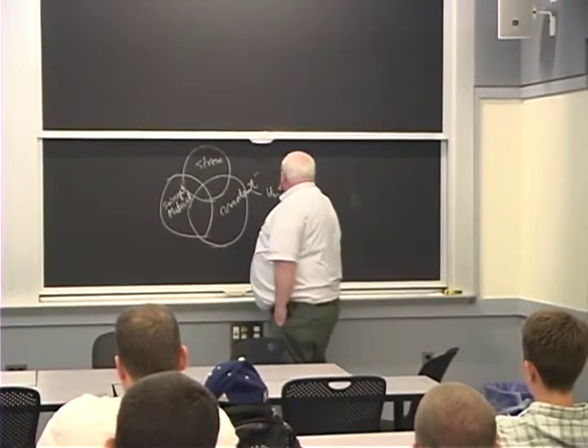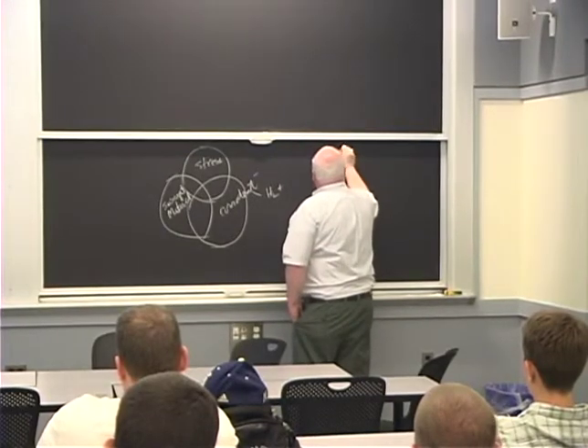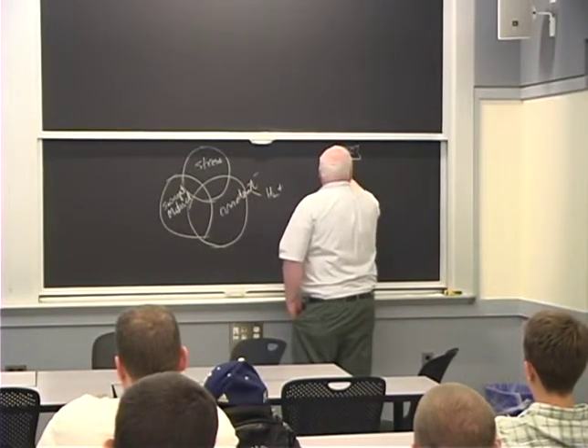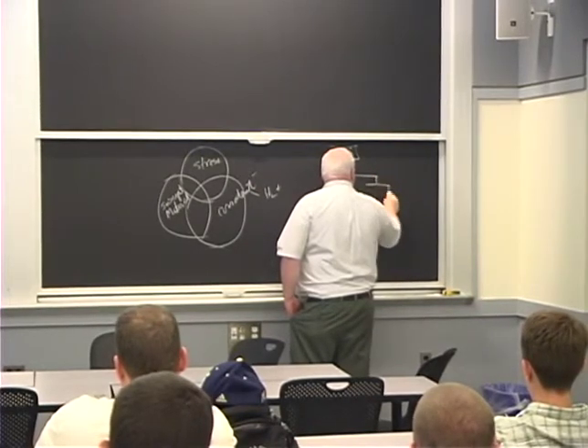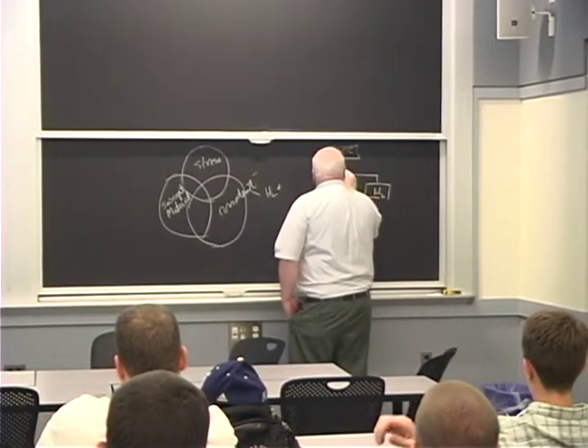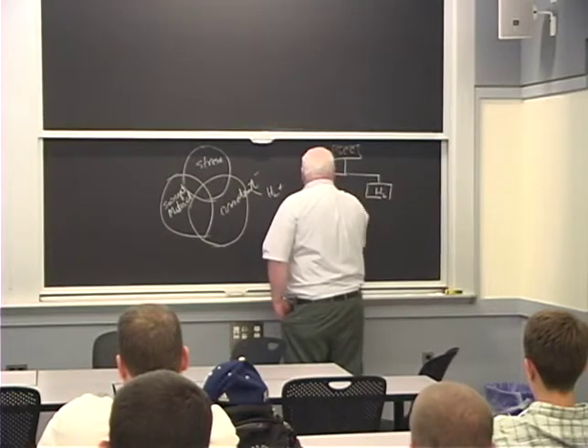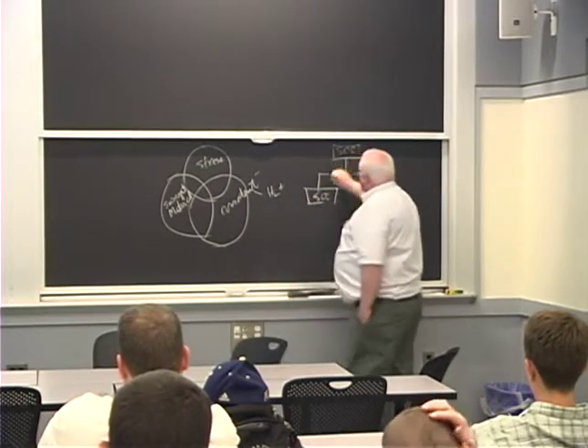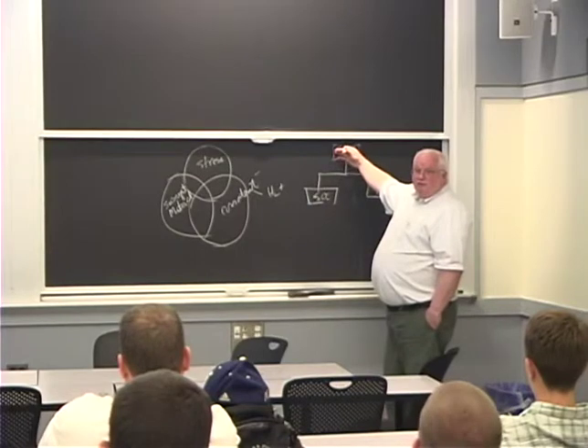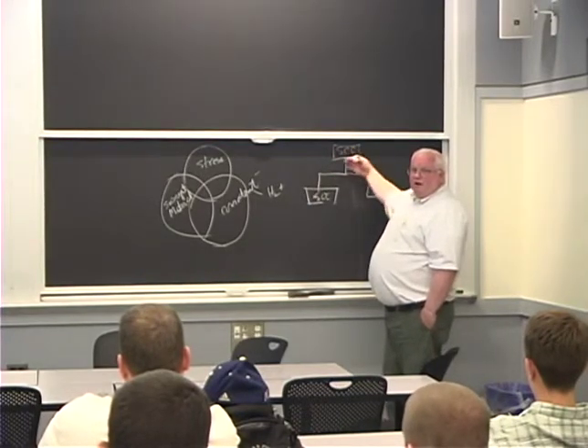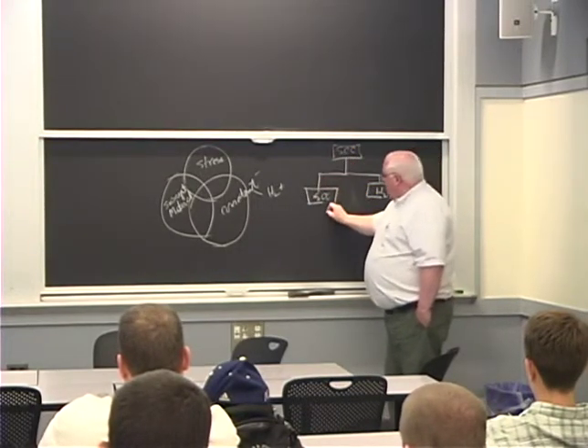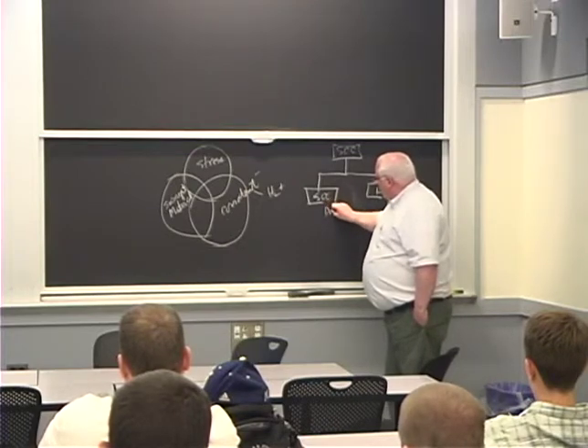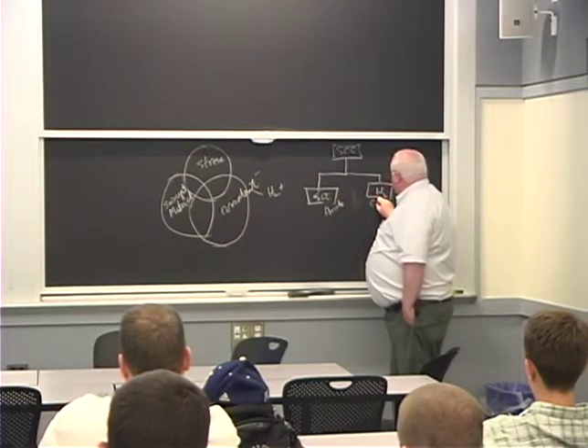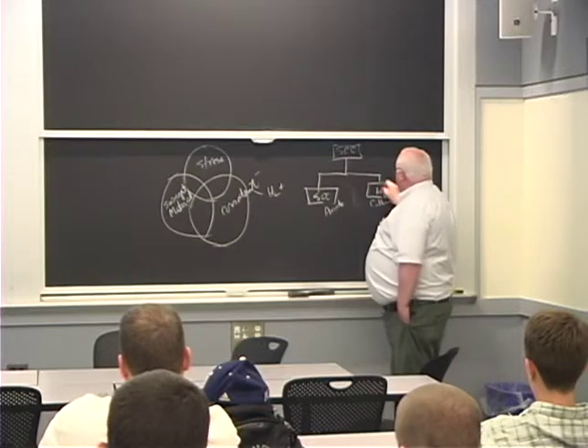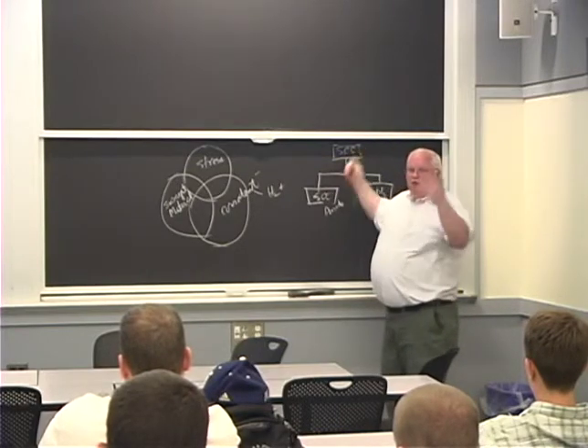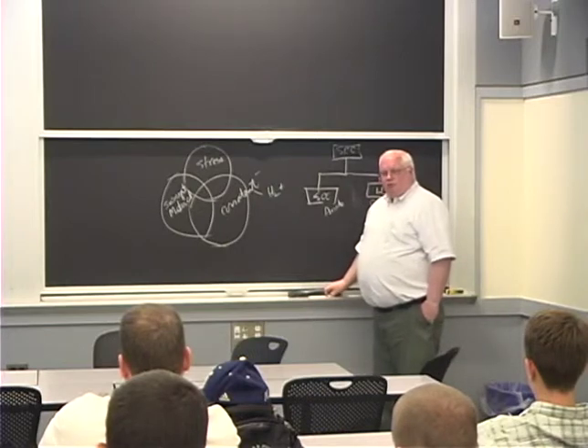So if I want to say under stress corrosion cracking, I can separate that into hydrogen cracking and stress corrosion cracking. And the problem we have is we're talking about stress corrosion on two different levels. One, we're including hydrogen cracking, and the other one, we're separating it out as this is anode, and this is cathode. And this, we're using stress corrosion cracking more generally, too. We don't care whether it's anode or cathode. Does that help? Yeah, it does.